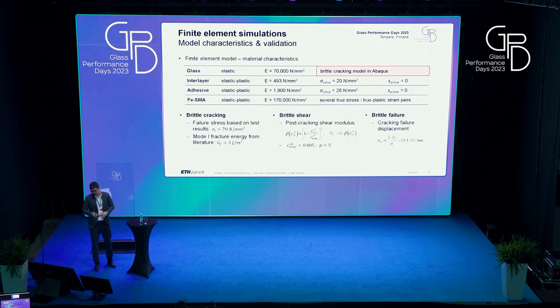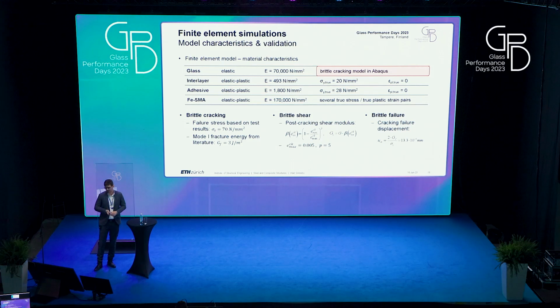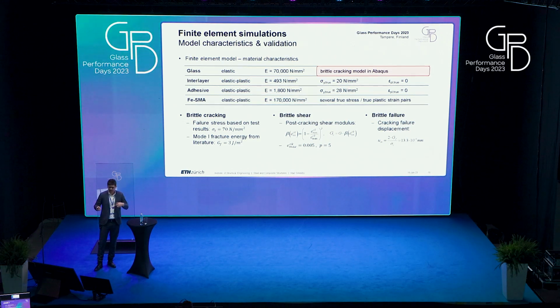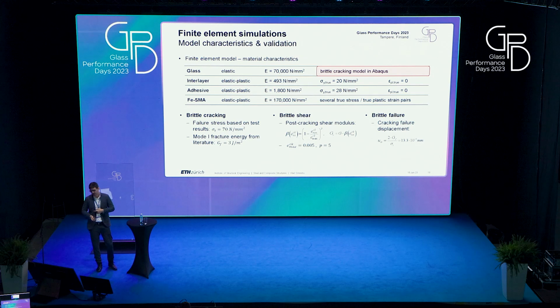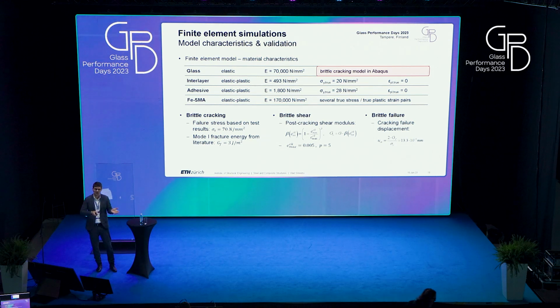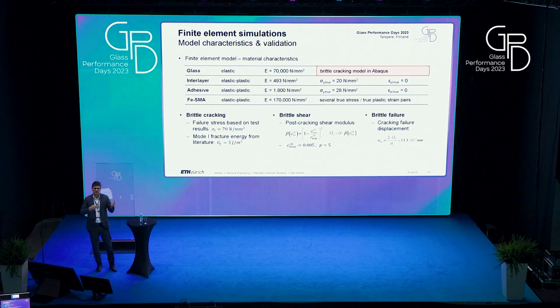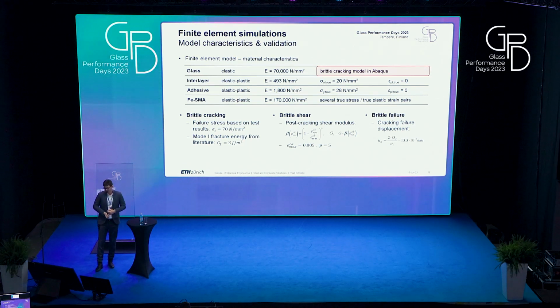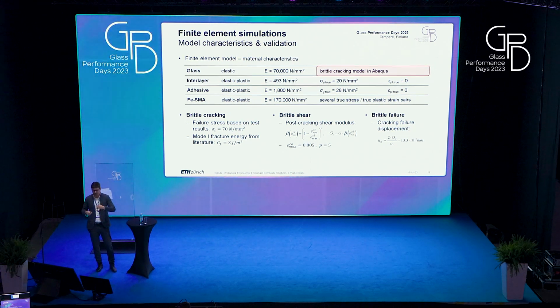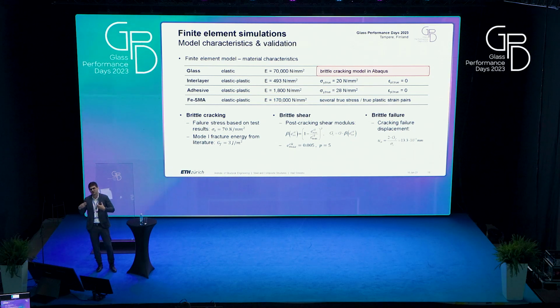For the glass, we used an elastic material model including this brittle cracking model from Abaqus. For these, you have to define a failure stress. Here, for the simulation of the test we performed, we assumed the failure stress of 70 Newton per square millimeter, although we had annealed glass, because it was the value we measured with the strain gauges in the test. And what this model also includes is these properties for brittle shear and brittle failure. The brittle shear is considering the shear modulus of the cracked glass beam, and the brittle failure defines that the elements in which this failure stress is reached are removed from the system.